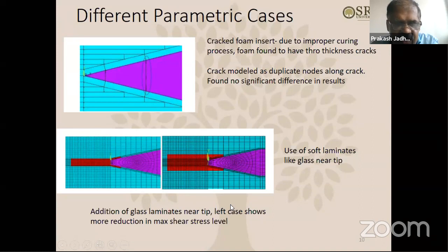Also, there were some other cases, like use of soft laminates like glass near the tip. As you can see, the maximum stress or strain concentration is mostly occurring at the tip. Although this blade is made of carbon composite, how about we insert some glass plies there? Glass is a softer material compared to carbon. So if we insert this softer material near the tip, what is going to happen? This is one of the cases that we tried. If you insert the glass laminate near the tip, it shows that a reduction in the maximum stress level was achieved.